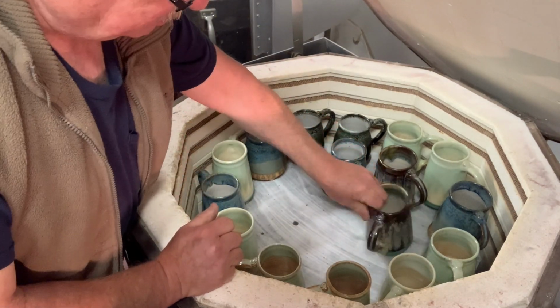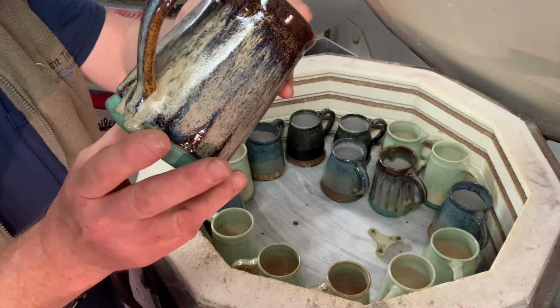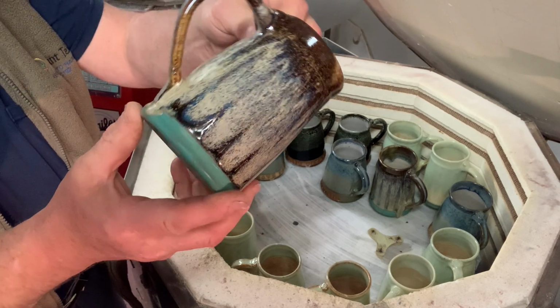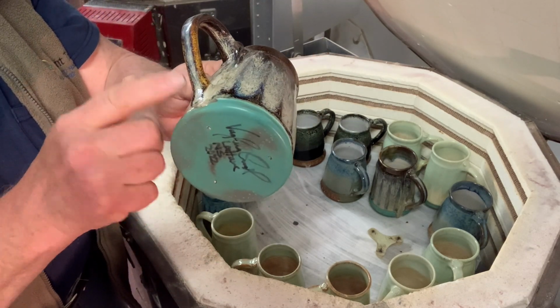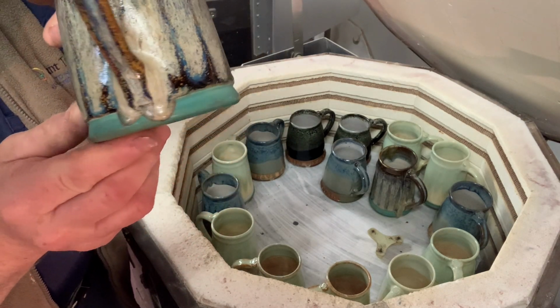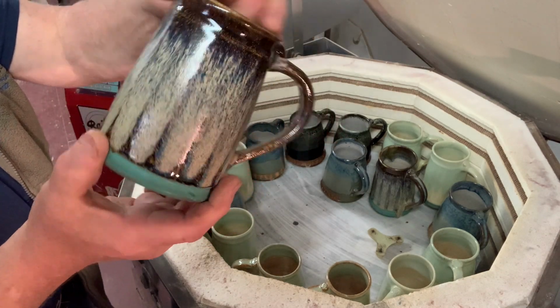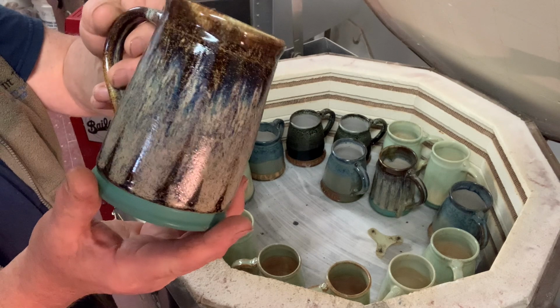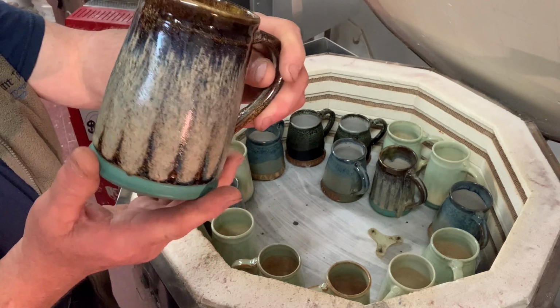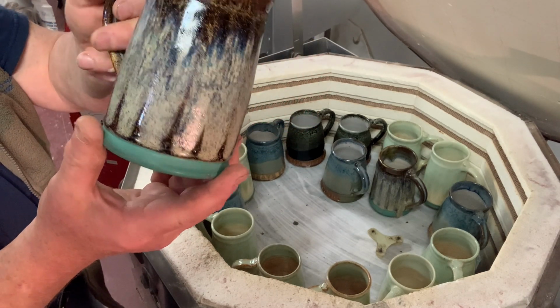And then I have a whole bunch of the usual colorings that I have. And this is a slight adjustment to my firing schedule. I lowered it by 6 degrees Fahrenheit because the last firing I had some runs coming off the edge just where the handle wasn't. Whew, look at that. 6 degrees difference stopped it doing it. Anyway, that's Temmoku Gold with variegated blue and oatmeal. Temmoku Gold, bright blue, floating blue out of the book Mastering Cone 6 Glazes, and my oatmeal.